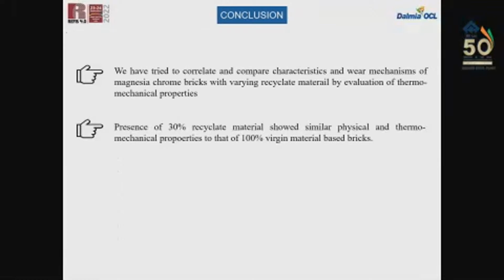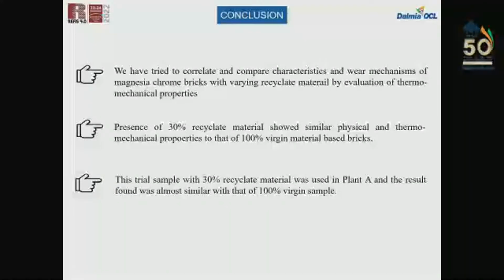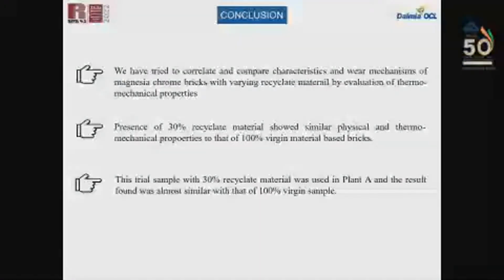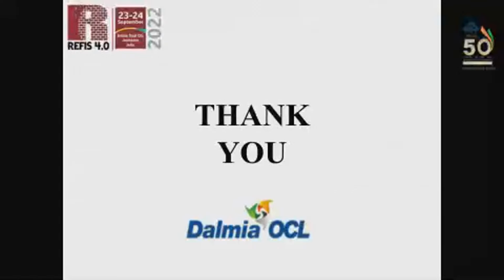I need to conclude by saying that whatever recycled material we are using, up to 30% it is performing as good as 100% virgin material. One thing to be said is that the recycled material quantity or rather quality should be better. It's not the total grog mix that was used, and we have got a similar life. This is very important for us so that we can stop the import of material from foreign countries, and we can use our own recycled material to make refractory. Thank you all from my side.